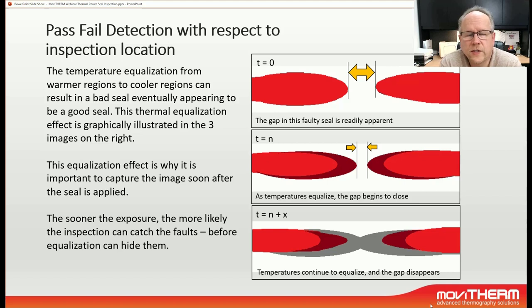So this illustration is to demonstrate what happens over time when using a pass-fail algorithm to look for faulty seals. As we have learned, the longer we wait after the sealing location, the more the thermal energy blurs from the hotter region into the colder region. So if we had a faulty seal, meaning a gap where there's little or no energy, a cold spot, and we would perform some image processing on this, represented here by the red region. The red region is basically saying this portion of the seal is good, it has sufficient energy in it, and here would be a gap, and this could be a weld problem or something like that, or a crease in the material, or a missing adhesive. Any sort of things like this could cause this fault.